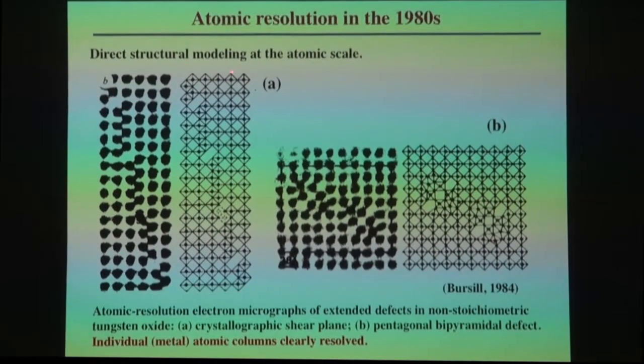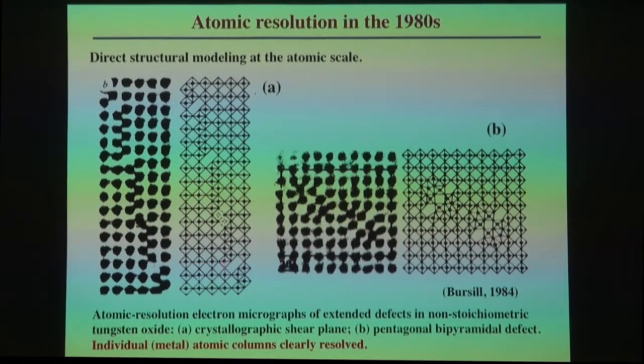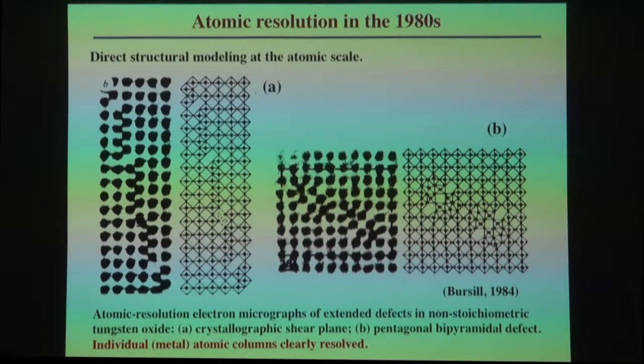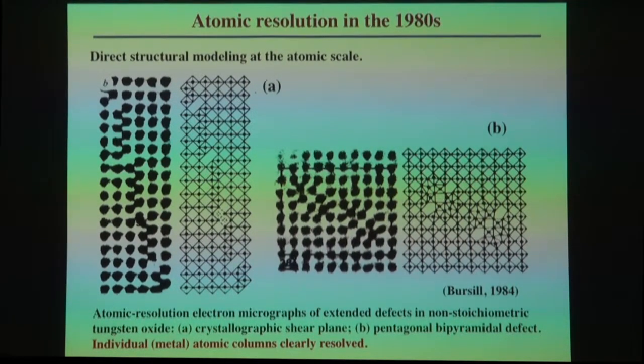It's very straightforward to take an image like this and build a structural model. Even in the case of a very complicated structure, like this pentagonal bipyramidal defect, it's possible to say, okay, here is the image, and I can start to build the structural model. In some cases, you'll see you have this little pentagon. The pentagon is filled in this position, and it's empty, and it's filled. And so the unit cell of this material, a very complicated unit cell, but you can identify the filled pentagons and the corresponding empty pentagons.